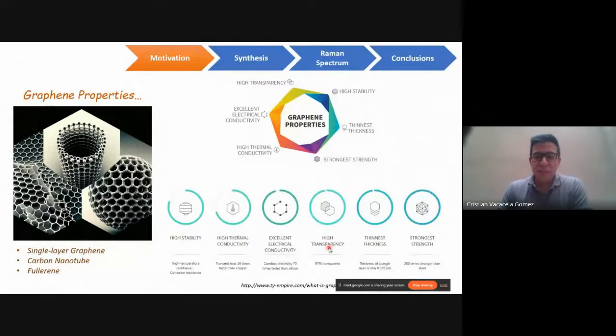Why? Because they identified different physical and chemical properties. For example, graphene shows high temperature resistance and corrosion resistance. It transmits heat 10 times faster than copper, it has a conductivity 70 times higher than silicon, 97% transparency, and the thickness of a single layer. Remember, this is made of carbon with only 0.33 nanometers.